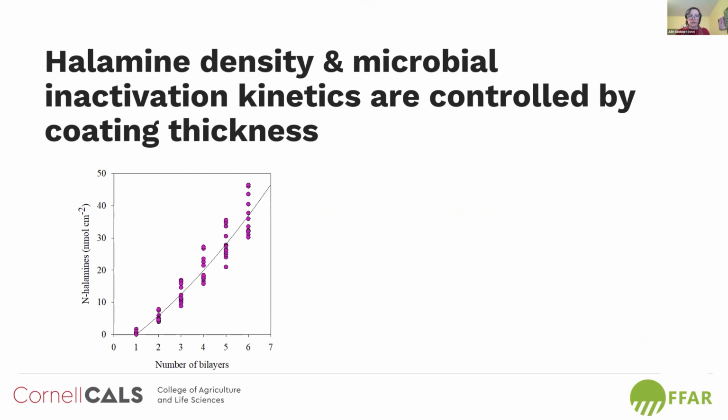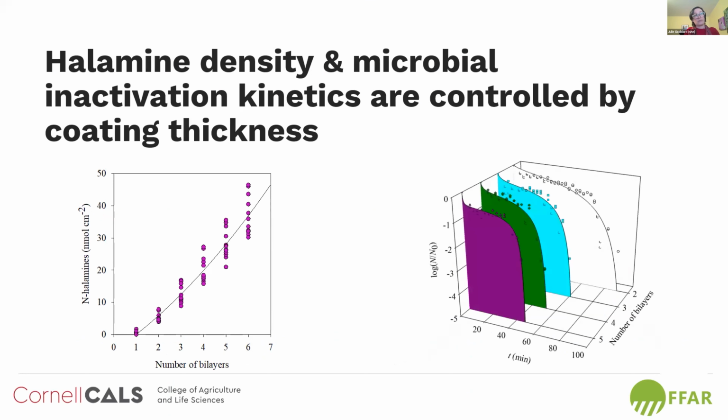We've shown in our research that as you increase the degree of the coating, so the amount or thickness of the coating, you can then manipulate the microbial inactivation kinetics. And so we can see here with increasing number of bilayers up to 5, we're able to show a log reduction value that achieves its theoretical maximum, or theoretical total kill, in under an hour.